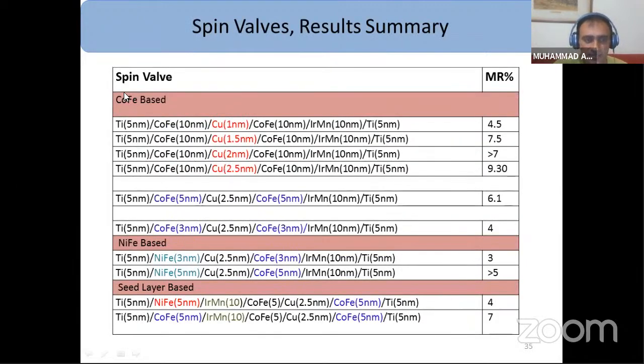The result summary is for the cobalt iron based spin valve and the nickel iron based spin valve with the seed layer. We have got up to 7% with annealing on the seed layer base, and without annealing, I have got a maximum MR value of 9.3 with the cobalt iron based spin valve.